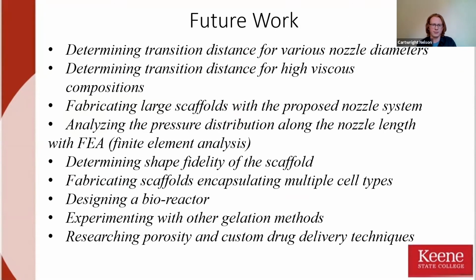In the future, I've been working on the transition distance for different nozzle diameters and for highly viscous compositions. I've also been working on different material compositions for fabricating large scaffolds, which some use pre-crosslinking and some use post-crosslinking, but that's being looked at because, as you can see, a lot of those scaffolds are very small.